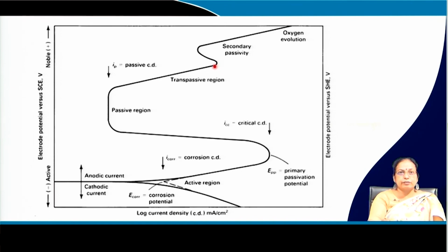Again, if fresh surface is exposed, there may be secondary passivation behavior, where again there is passive film formation. Then certainly after a certain period of time, when the E value increases to a large extent, there will be oxygen evolution. That is the case where the component stops working, or you cannot use the component at all.